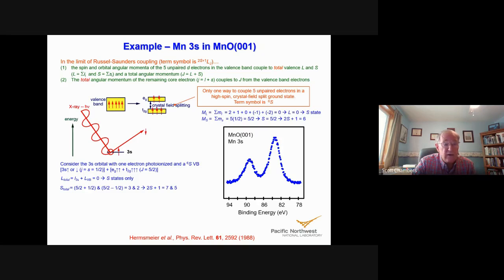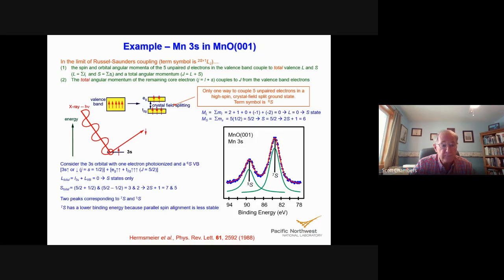The total spin is either going to be 5 halves plus 1/2 or 5 halves minus 1/2, depending on whether the spins in the valence band couple parallel or anti-parallel to the one in the core. So that means that 2S plus 1 is either going to be 7 or 5. So we expect 2 peaks in this spectrum, a heptet S and a quintet S. And we see that our 2 peaks are there, and the correct assignment is that the heptet S is the lower peak and the quintet S is the higher peak. The reason for that is because the heptet S has a lower binding energy because of the parallel spin alignment. It's less stable. And you can also tell because of the relative intensities, which one has 2S plus 1 equals 7 and 2S plus 1 equals 5.